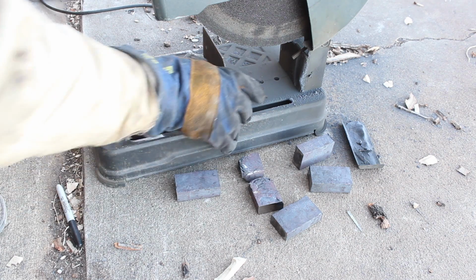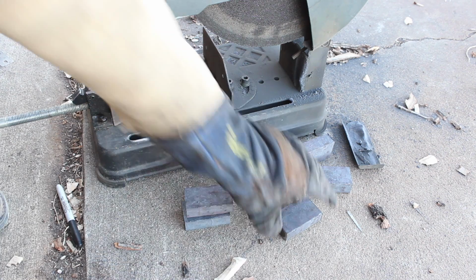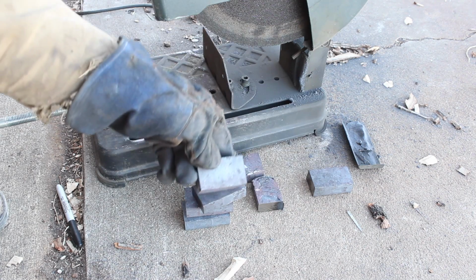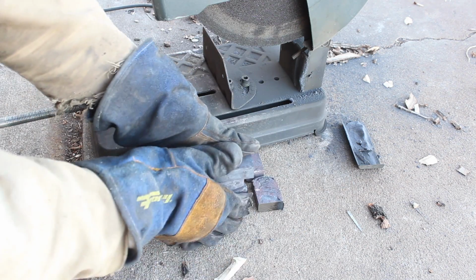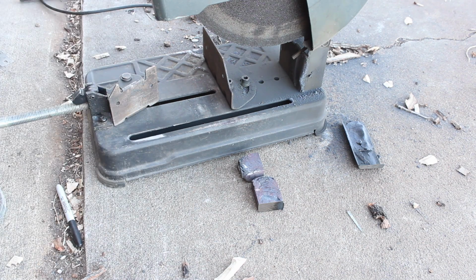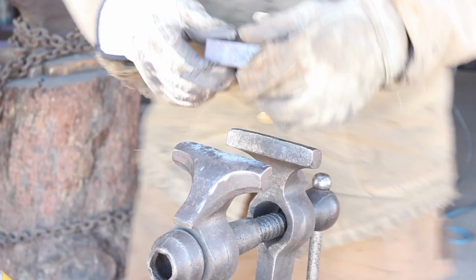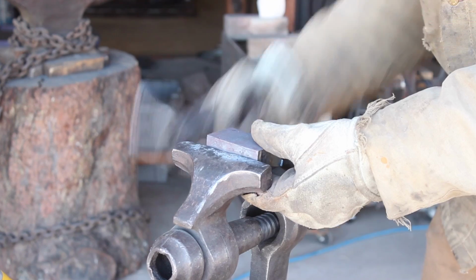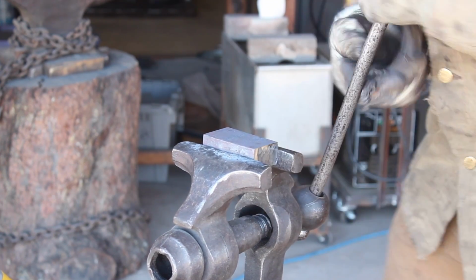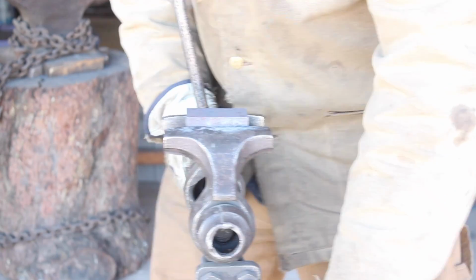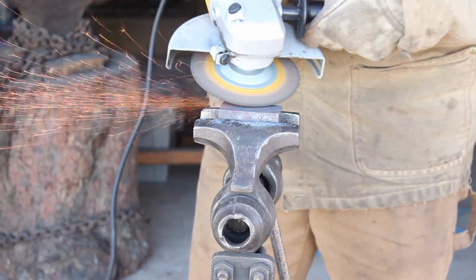So I need to cut this up into 5 pieces, and there we go. That's going to give me just over 200 layers, which I find is a really good layer count for most knives. It allows you to see the pattern still when you're starting with about 1/8 inch thick material, and just provides a good solid billet. That's what I like to do most of the time, between 200 and 300 layers.